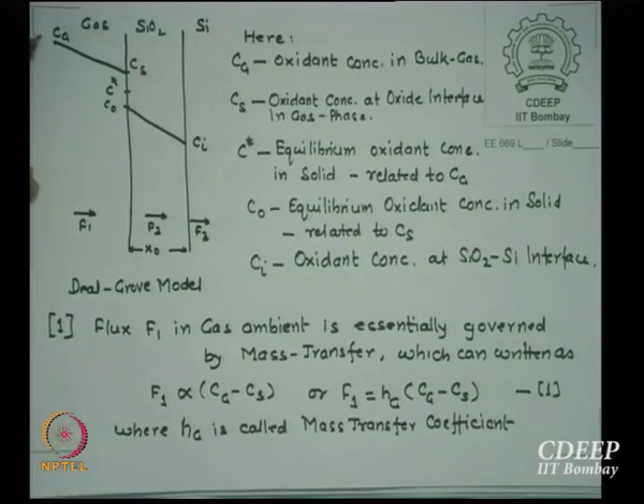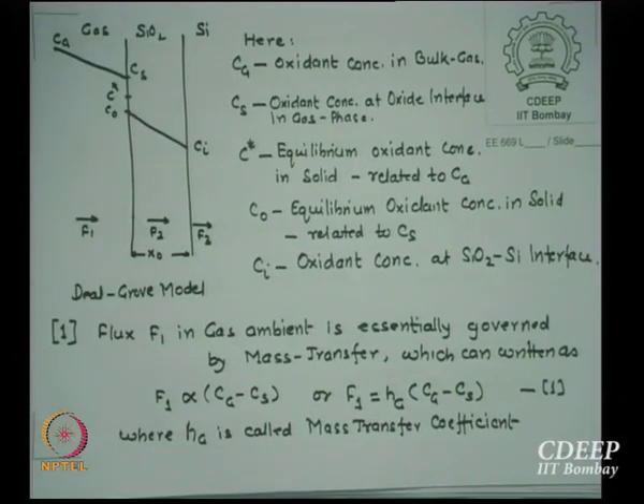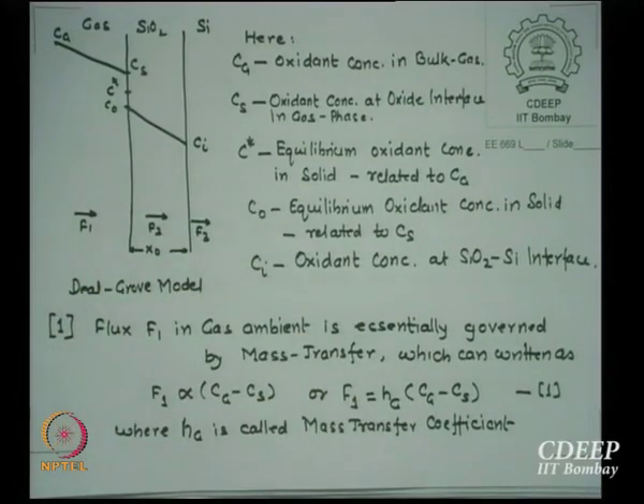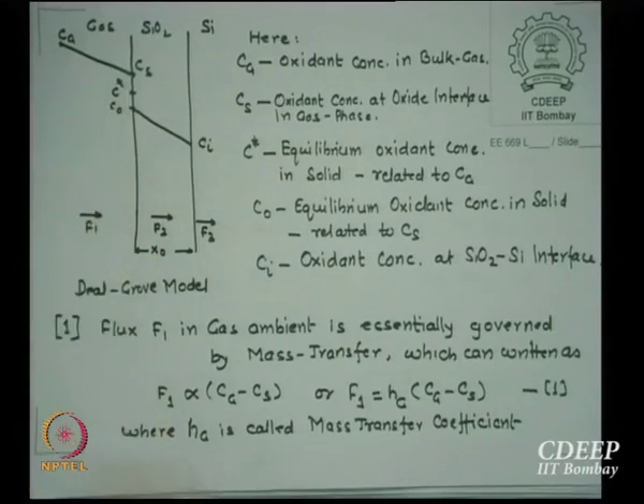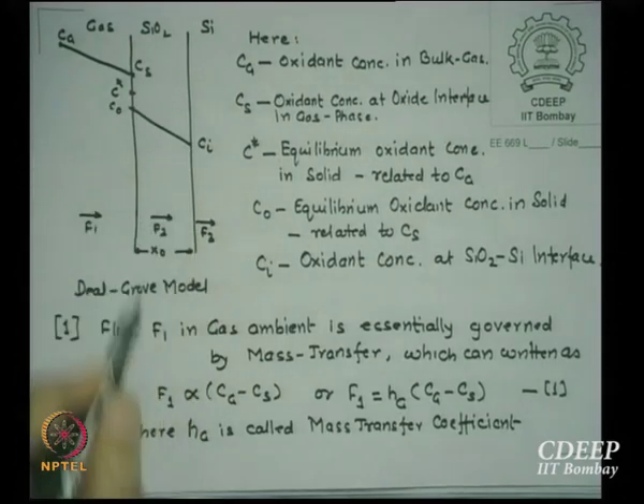Now these are called gas phase concentrations. The equilibrium concentration in the solid can also be found, and we define C star as the equilibrium oxygen concentration in the solid related to this Cg. Cg is the gas phase concentration and C star is its equivalent in the solid phase, whereas C0 is similarly the equilibrium oxidant concentration in the solid related to Cs. So this relates to here and this relates to here, okay. Then we say the initial oxide thickness is X0, and the initial concentration at the interface is Ci, okay.